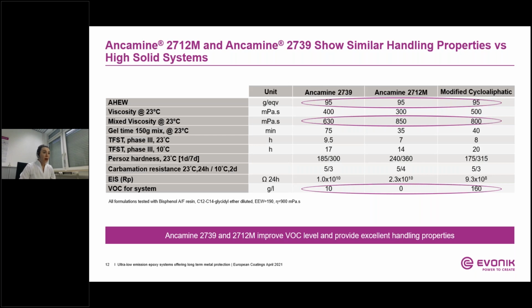So both products have been formulated to provide a 50 pHr loading with a standard liquid epoxy resin. The unique advantage of the two products is the low mix application viscosity, which is achieved at lower than 10 grams per liter VOC, whereas the standard cycloaliphatic has a VOC content of 160 grams per liter due to the presence of benzyl alcohol. Additionally, the new curing agents exhibit fast drying.